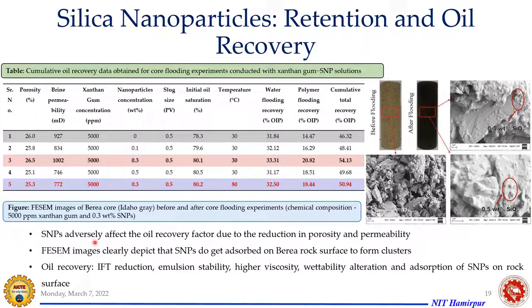So you can see nanoparticles adversely affect the oil recovery factor due to reduction in porosity and permeability. So when you extend your nanoparticle concentration beyond the optimum, that is 0.3 is what we have detected in this case, there will be a blockage, so it would adversely affect the oil recovery factor due to the reduction in porosity, and the permeability is hampered, so you cannot have higher oil recovery beyond a certain range. And the FESEM image clearly depicts that the nanoparticles do get adsorbed on the rock samples to form these clusters, as highlighted in red in this figure.